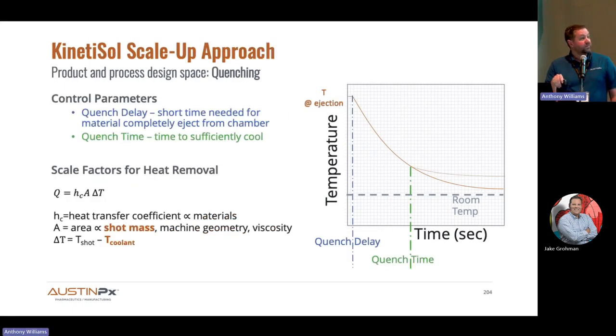So the other aspect of this is, there are parameters, and they'll show up in our batch records. Maybe for some systems, we might find that they become a critical process parameter. I doubt it. I really do doubt it. But the two parameters are quenching delay and quench time. And so the material leaves the system. It needs to get into a location where we can quench it and take the heat out. And we need to tell the machine how long to do that. And where we set that time is where the cooling curve for the system would diverge.